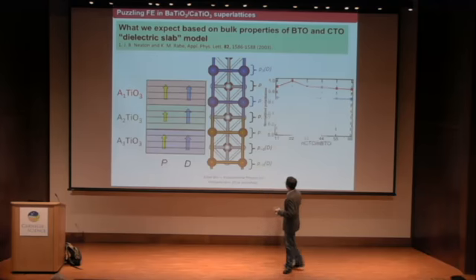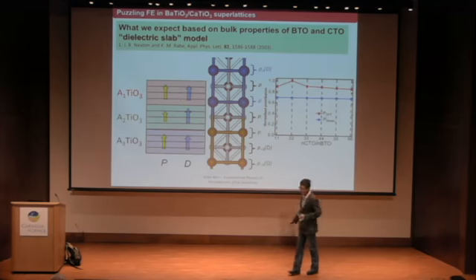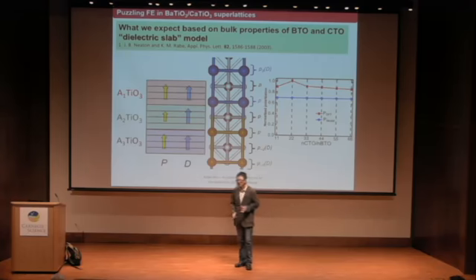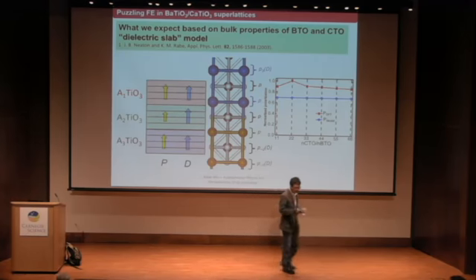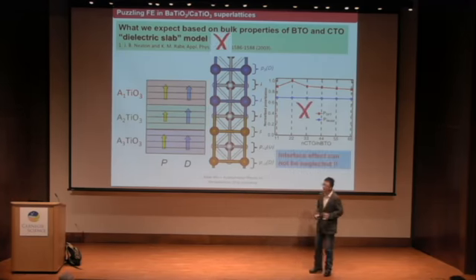Then if it works, you will get the blue line. It's far below the actual DFT calculations. So what does it mean? It means that simply the interface effect cannot be neglected.